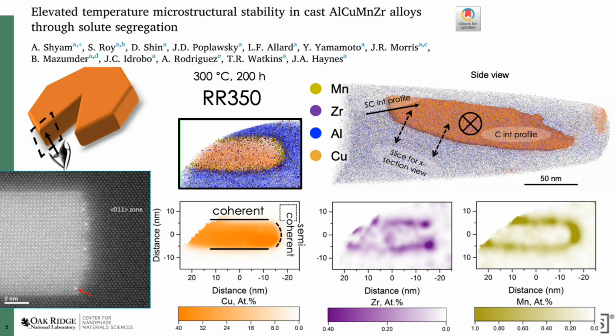Atom probe tomography results of a 300 degrees C 200-hour exposure reveal that zirconium segregates to the coherent interfaces, while manganese segregates to both the coherent and the semi-coherent interfaces, with additional segregation to the semi-coherent interfaces. Density functional theory and phase field simulations have shown that interfacial energy reduction as well as solute drag effects increase the stability of these precipitates from this solute segregation.